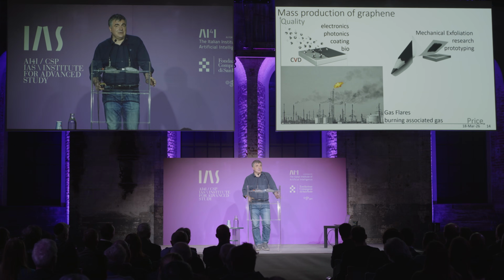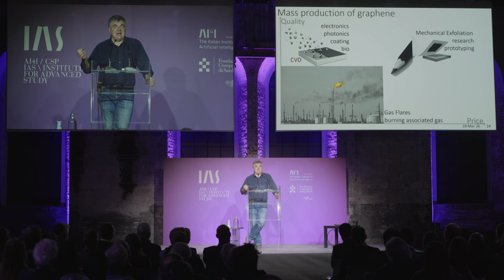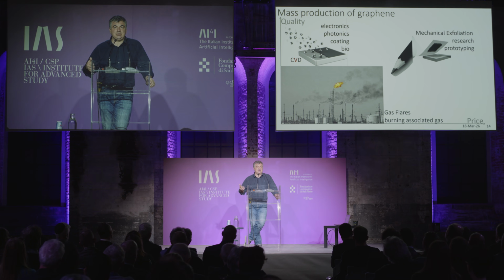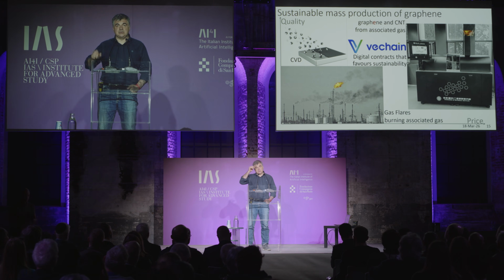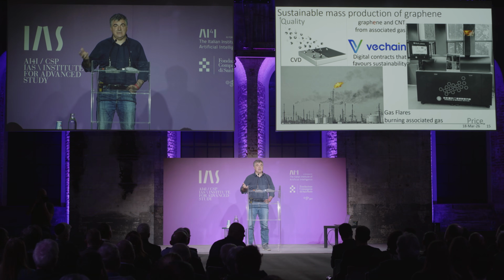But of course, every joke has a bit of truth in it, and I'm sure that you've seen pictures like this everywhere in the world, where we burn the associated gas at every petrochemical or refinery plant. It's even worse at the oil wells, where we burn a lot of associated gas because it's just not economical to transport it. And methane is a much worse greenhouse gas than CO2. It's better to emit CO2 than methane, but in those flares, we've got everything we need to produce graphene. We have the high temperature, we have the carbon-containing gas. So we developed machines which can turn this methane into functional carbon.